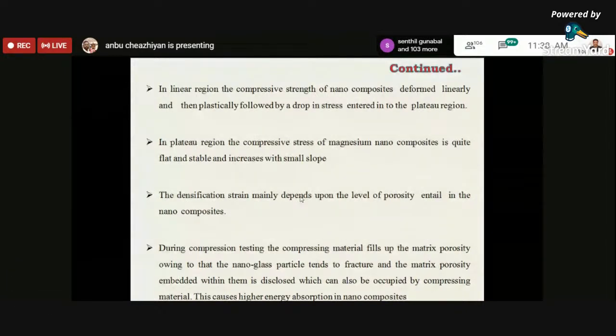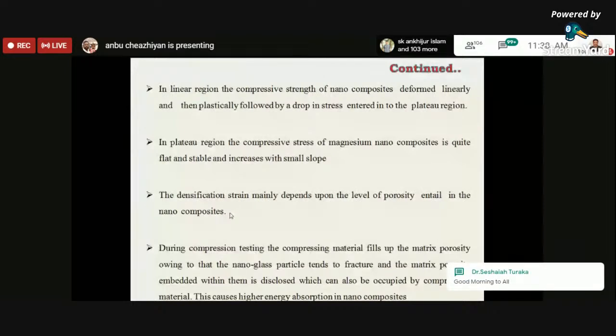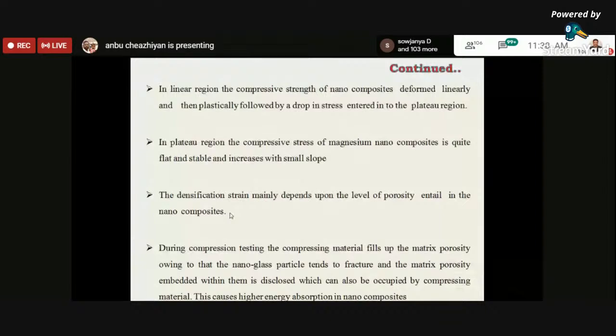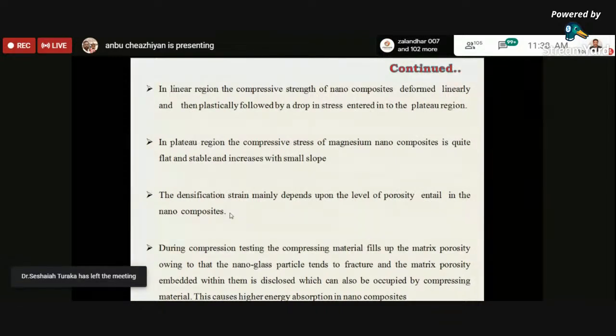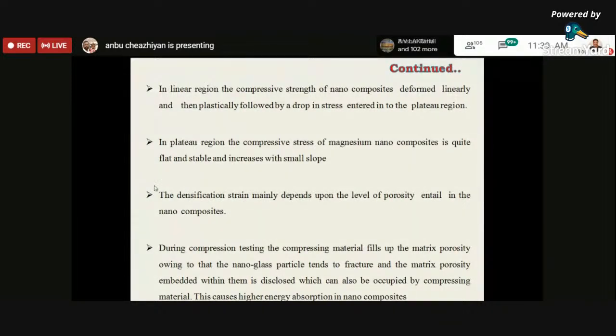So during compression testing, the material fills up. Sometimes there will be some matrix porosity in the material, as I showed in the microstructure. That can also be filled during compression. That is, the matrix material fills up the matrix porosity. So when the nanoglass particles tend to fracture, the matrix porosity embedded within them is disclosed and filled due to the compression. This causes the enhancement of compressive properties of nanocomposites.